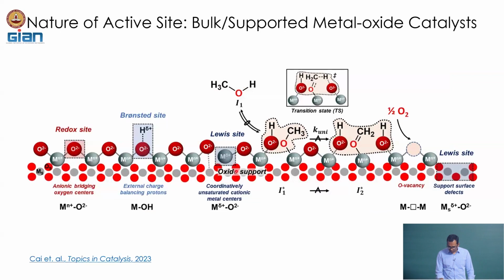If we look at one of the schematics of the metal oxide catalyst, and by the way this is not just a representative catalyst, metal oxide catalysts compose more than 50% of the industrial catalysts. So, they are real in nature, and what we see is that on the catalyst there can be different types of sites. You can have redox sites, you can have different types of acid sites. It can be a Bronsted acid site, it can be a Lewis acid site, there can be defect sites, there can be vacancy sites, and all these sites take part in the reaction to a different extent. So, it may happen that all of these sites are participating in a reaction, or it may happen that only a few of these sites are actually participating in a reaction, right?